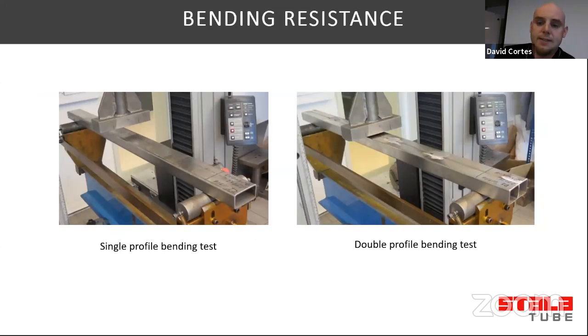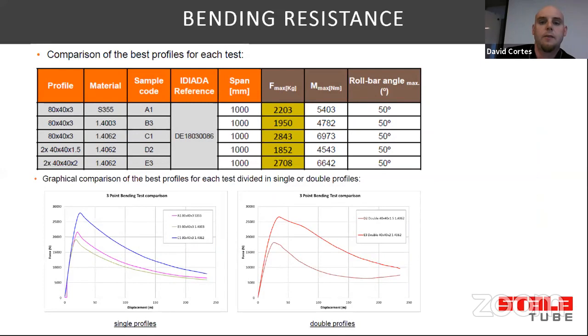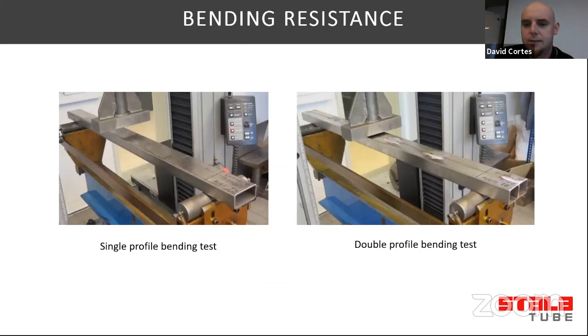Then we have done some bending resistance tests. Here are some photos from the actual test. And here we have some results from those tests. So there you can also see the profile size on the left-hand side. And there is the steel grade. We had there 3 different steel grades, this carbon steel S355, then ferritic stainless steel, and then 3 different kind of Lean Duplex profiles. So as you can see, the best bending resistance comes from the profile where we have welded together 2 40x40x2 profiles. So you can see that double profile on the right-hand side.